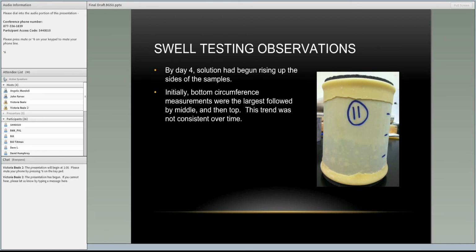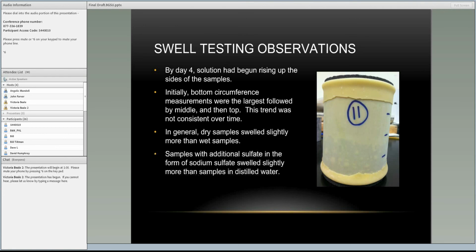And a physical description of the swell samples. After 56 days of measurement, the latex membranes were removed and the samples were allowed to air dry. So here you can see a lot of visible cracks in the samples. We cut the samples in half with a diamond saw and then allowed them to air dry.